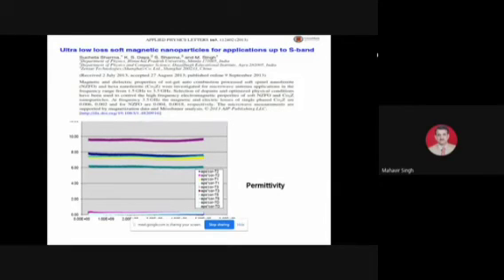So these are the results. At the bottom, it is the imaginary part, and on the top, it is the real part. Dear friends, one thing is very, very important. If you want to use any kind of soft magnetic system in communication, the interesting part is that your real permittivity and permeability should be high, greater than 2. But the imaginary part, that is the loss, should be close to 0. In our struggle, we have controlled the electric part. Permittivity, we are okay. Our permittivity imaginary part is 0 and the real part is greater than 2. But permeability, we are still struggling. We are not able to control the imaginary part of permeability. Still, we are struggling there.